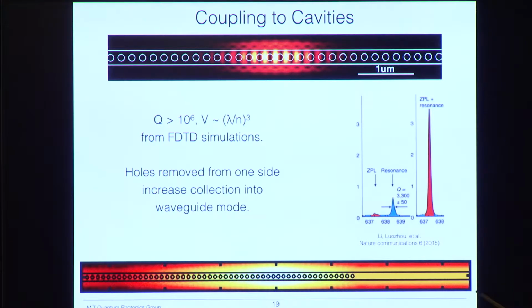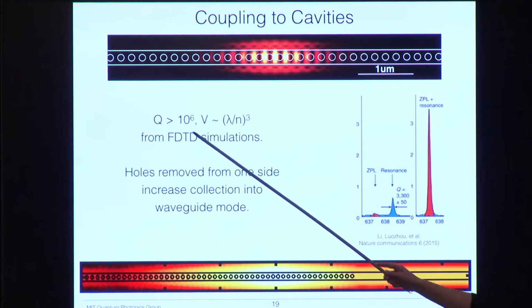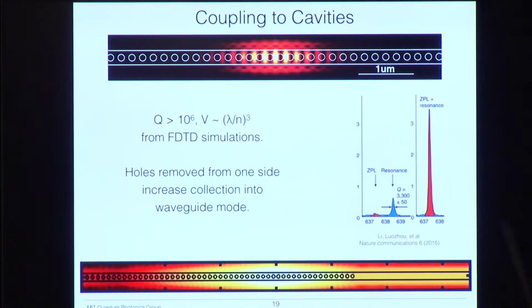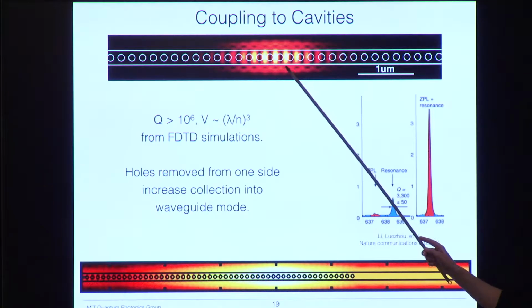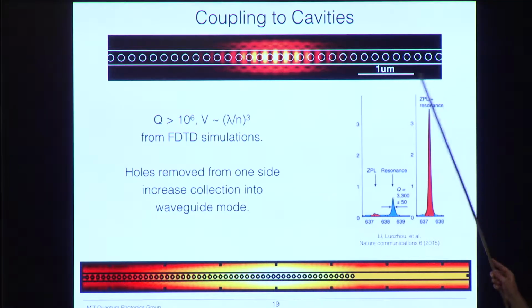So in simulation, you can get very high Qs, bigger than 1 million, and very low mode volumes, around the size of the wavelength within the material. So this cavity is a very similar cavity to the one I showed before. You can't really see the defect as well though, but the spacing between these holes is slightly smaller than in the band gap out here. We can also remove the holes on one side in order to get most of the emission into one direction out of the waveguide.